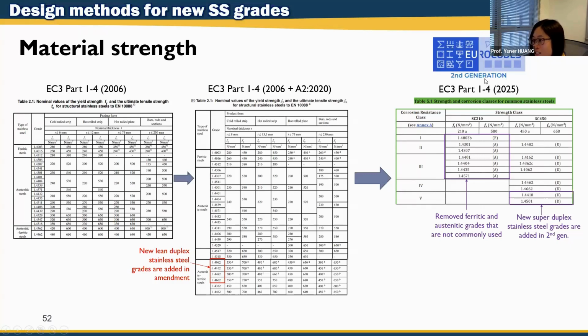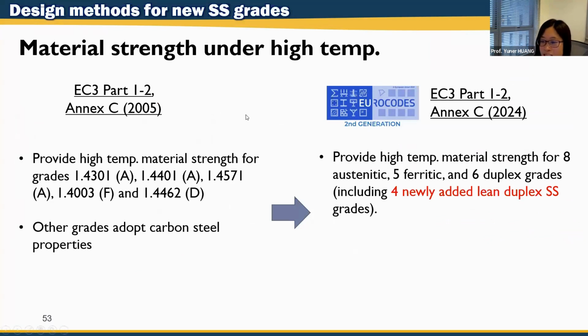And then in the second generation, in 2025, which is the latest version, they removed ferritic and austenitic grades that are not commonly used. They only leave the commonly used austenitic and ferritic grades. On top of this, they even added 2 more new super duplex stainless steel grades in the second generation. So we can see the trend of structural design is that they are paying more and more attention to lean duplex. And the same thing is for the fire design. So Eurocode 3 Part 1.2 is the fire design for steel. In 2005, they only had this grade. And then in 2024, in the second generation, they added 4 new lean duplex stainless steel grades. They didn't add anything else.